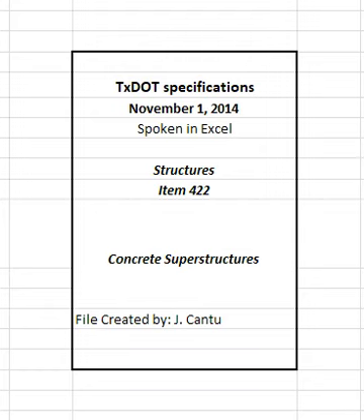4.1.5 Placement of equipment and machinery. Do not place erection equipment or machinery on the structure until the concrete has attained the design strength specified in Section 421.4.1, Classification of Concrete Mix Designs, unless otherwise approved. 4.1.6 Carting of concrete. Cart, wheel, or pump concrete over completed slabs after the completed concrete has attained a compressive strength of 3000 psi. Maintain curing during these operations.